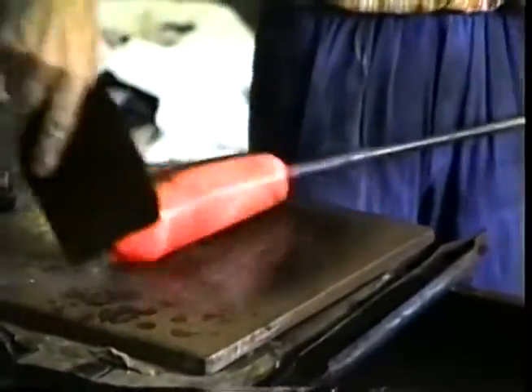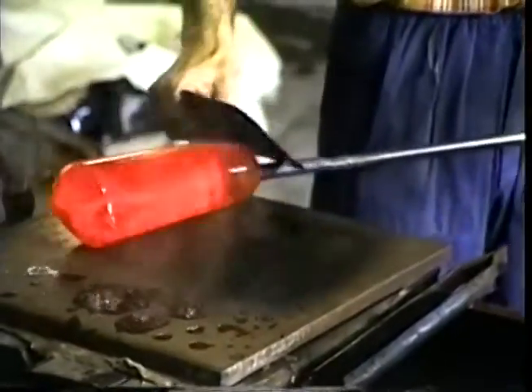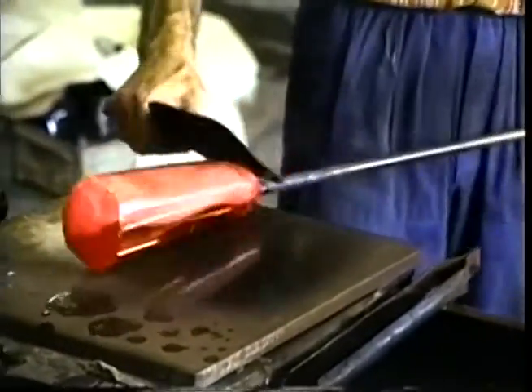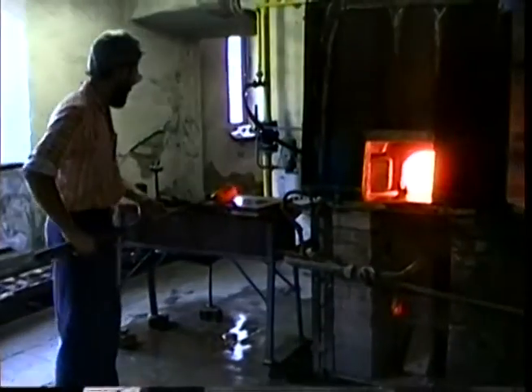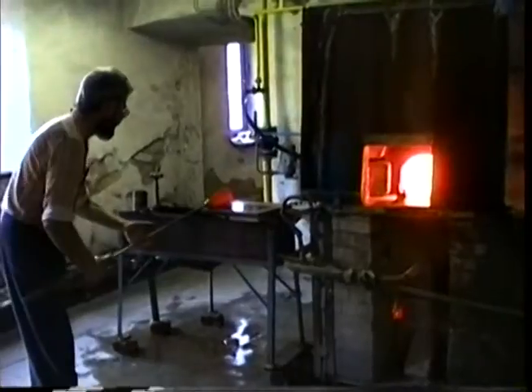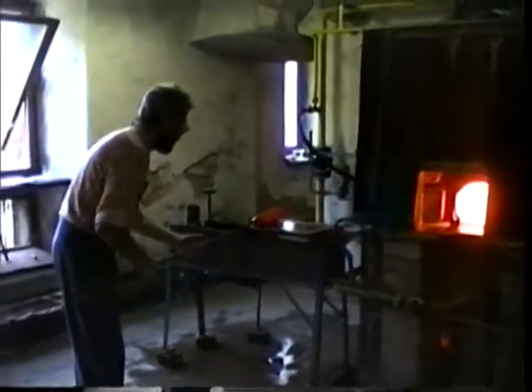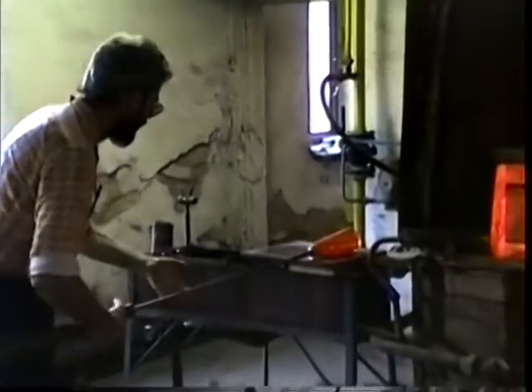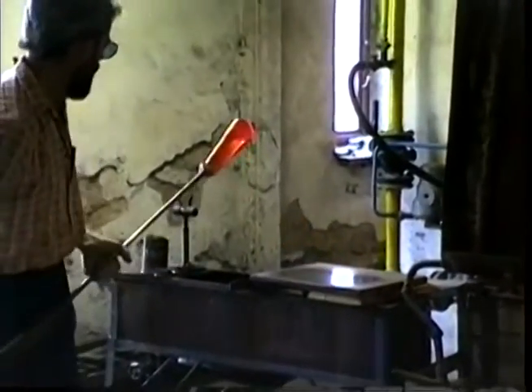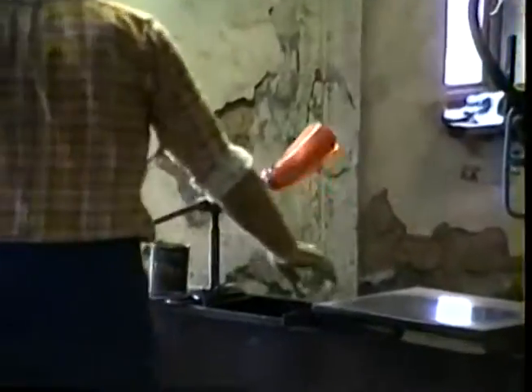They melt clear glass, so they take a heated chunk of the colored glass and put a layer of clear on one side. This will make a clear cabochon on top of the color when pressed. In a wound bead, any stripes or lines of color would be ruined. He's preparing the end for pulling.